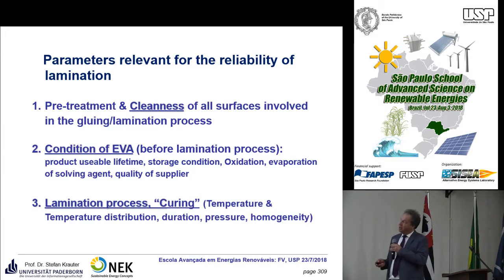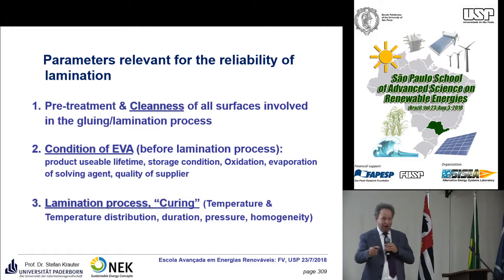Lamination process, the curing. This depends on temperature. Some of the manufacturers save time and money because they lower the temperature, thinking it will still work. And then the curing will not occur. Also temperature distribution. Some manufacturers use very cheap laminators, and then the surface is not even, and then some part of the module is hotter, some part is less hot. It is the same as cooking. If you have a cheap cooking plate, some part of the pan is hotter, some is colder. If you have a really good cooking plate which is really heavy, then the temperature distribution is more equal. Same issue here.